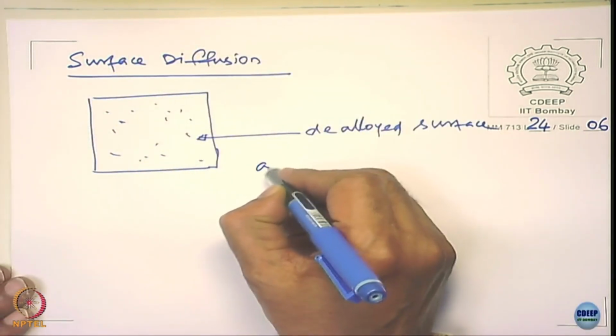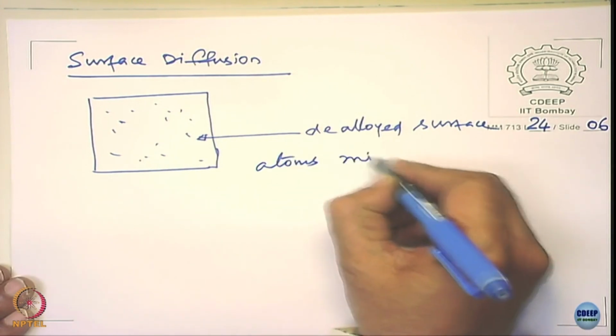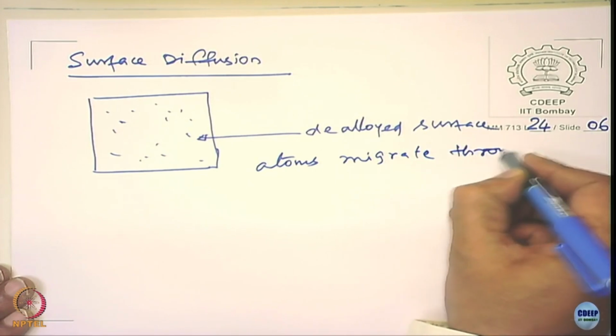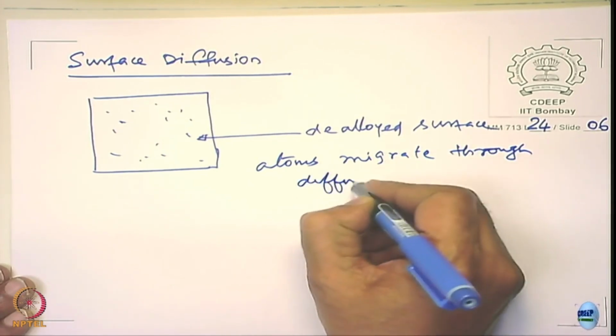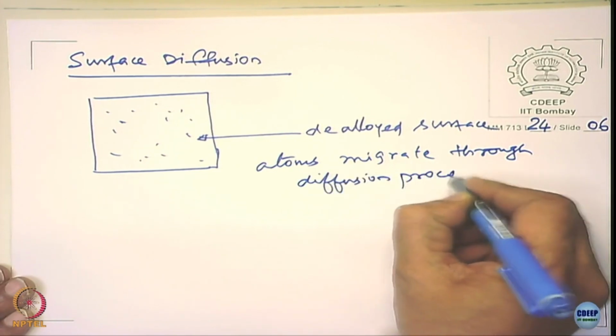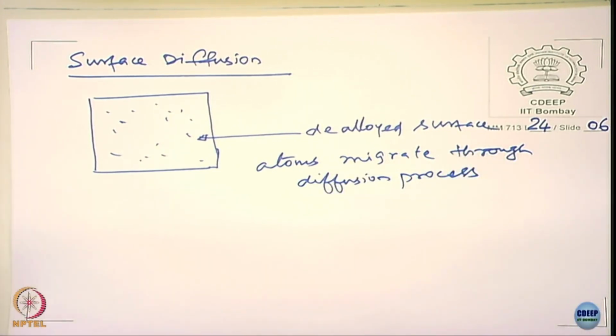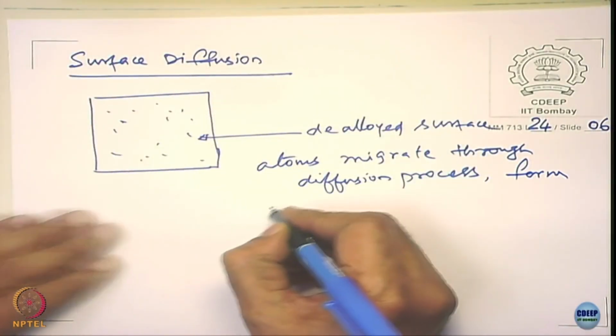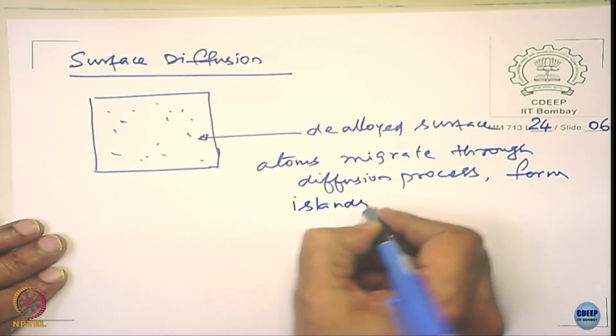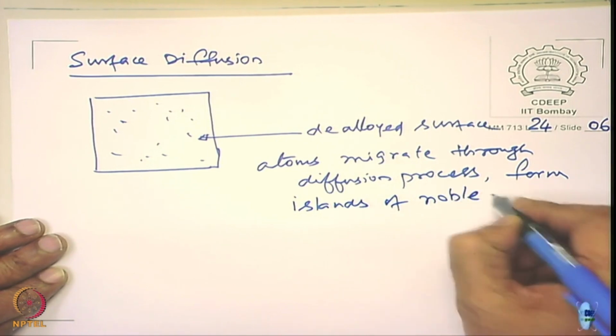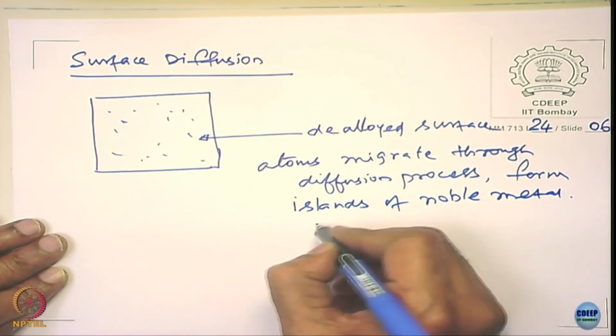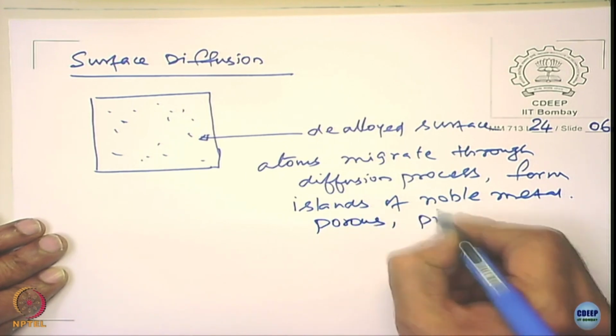Now these atoms migrate through a diffusion process. Because when the atoms are alone, the energy of the surface becomes quite large, right. So when the energy of the surface is more, then what happens? They try to agglomerate, actually. They migrate by the diffusion process and then form islands of noble metal clusters. You will see porous structures, you see pits.